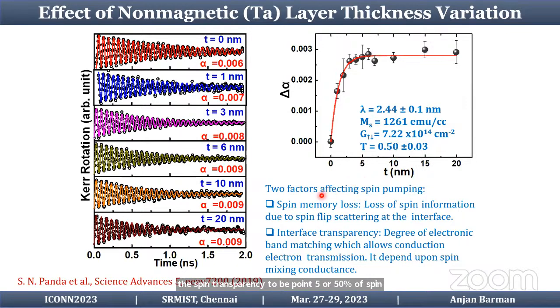Now, there can be two different factors which can affect the spin pumping. One is spin memory loss, where loss of spin information is caused by spin flip scattering at the interface itself, and the other is interfacial spin transparency, which depends on the degree of electronic band matching.